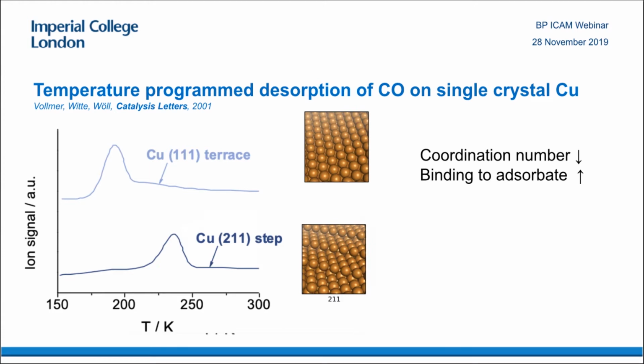So at my former group, we had a lot of UHV chambers, and we had some nice methods of probing surfaces of materials. One of our favorite methods was what's called temperature programmed desorption of CO. Essentially, what you do there is you adsorb CO at very low temperatures in vacuum, and then you measure the temperature that CO comes off. It doesn't dissociate, it just comes on and then comes off.